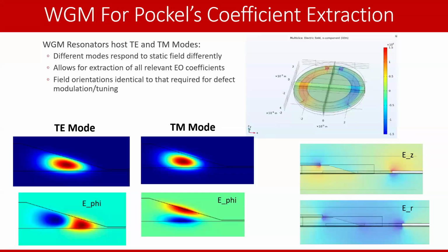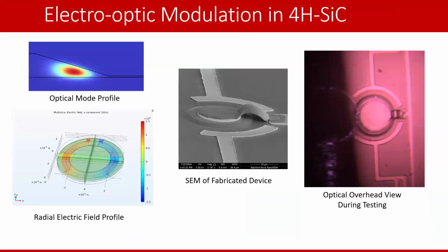And so in the resonator design that I just showed you, you could simulate the electric fields and take a look at the TE and the TM modes. Because the modes have different electric field orientations, they should behave differently under an applied electric field in terms of electro-optic tuning. This is an example of the TE and the TM mode in this whispering gallery mode structure. And this is the static electric fields that are applied when you apply static voltage on those electrodes that I've shown. And so I was able to fabricate these. This is the bridge shown before that allows us to put a different field here versus there.